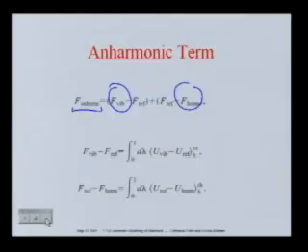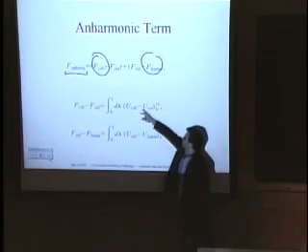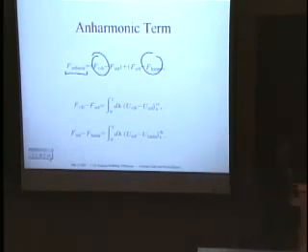So by introducing a reference potential, you are shifting a lot of the thermodynamical integration to the classical simulation, and you're just using the quantum mechanical simulations to sample the difference. And so this can be done with much shorter and much smaller simulations.